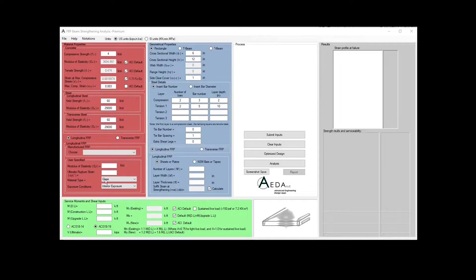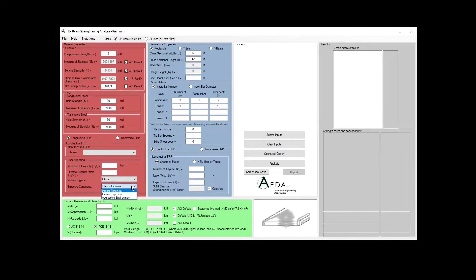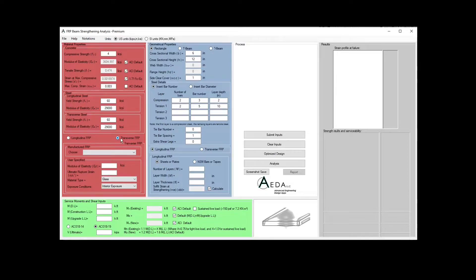For the transverse condition, you will define the material type — either carbon, glass, or aramid — based on ACI 440. The exposure condition is interior, exterior, or aggressive environment. The material type and the exposure condition will determine the environmental coefficient and the reduction in the rupture strain and the rupture stress.